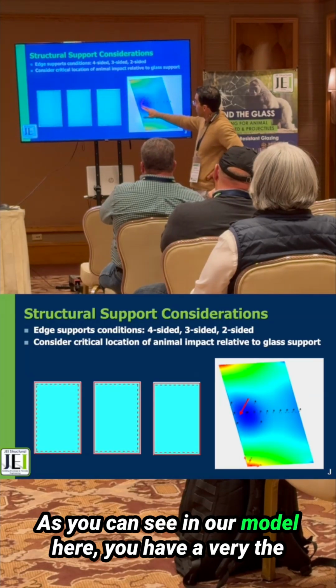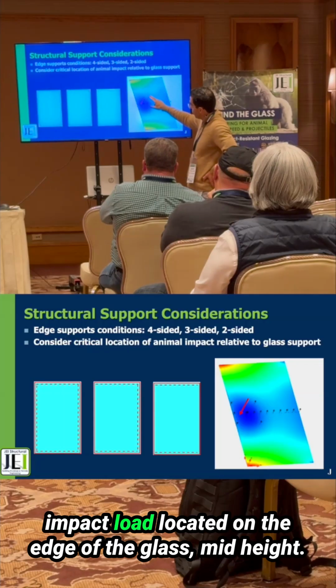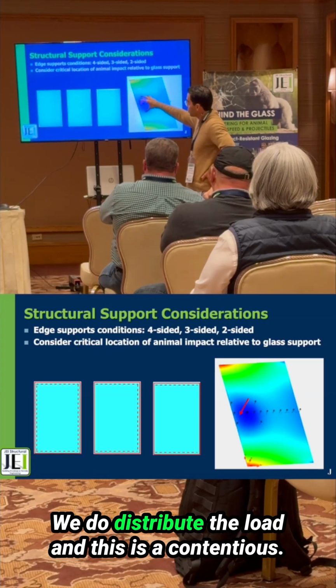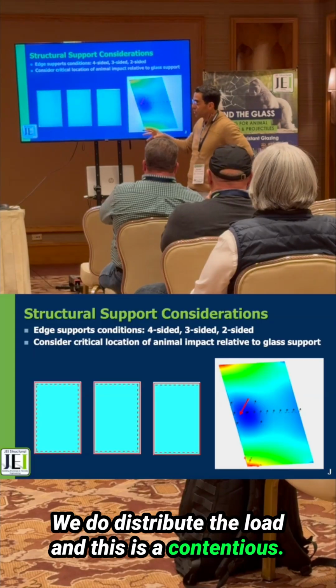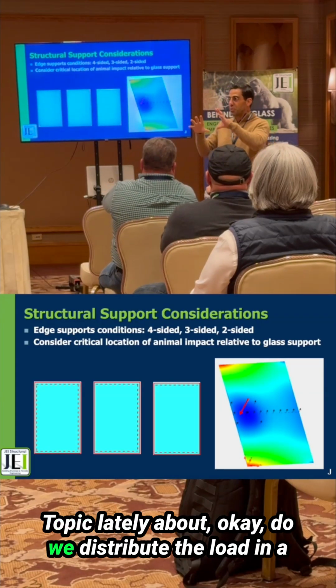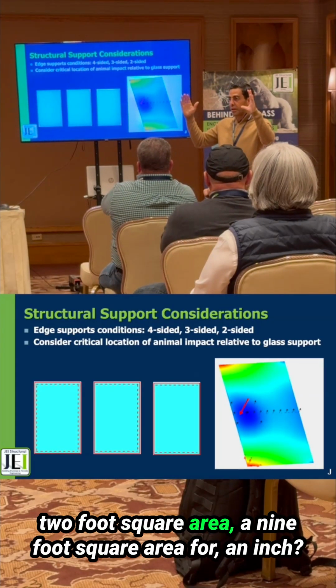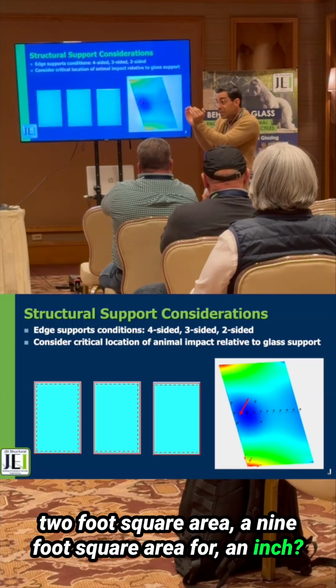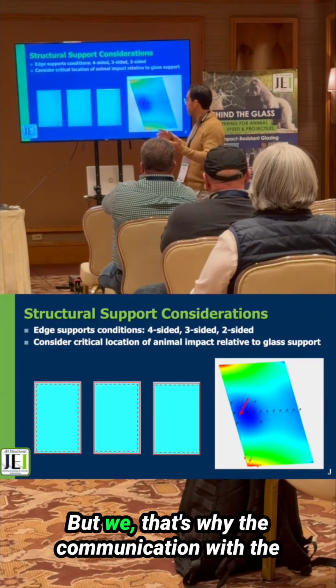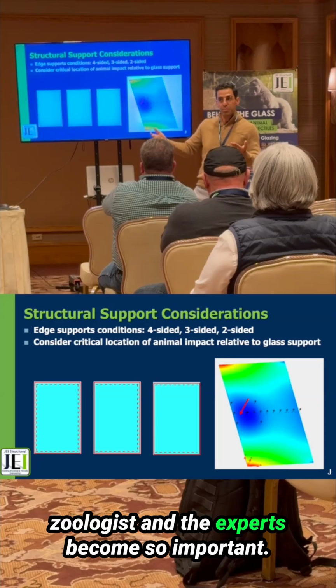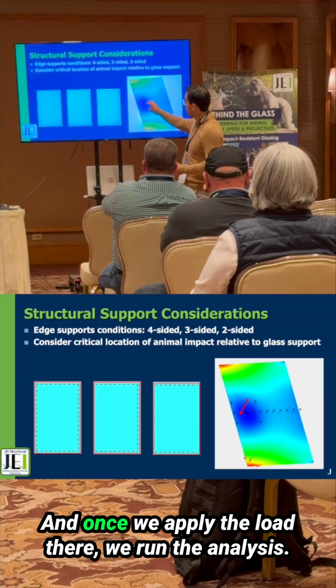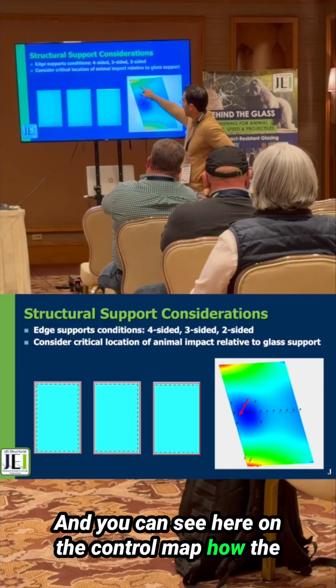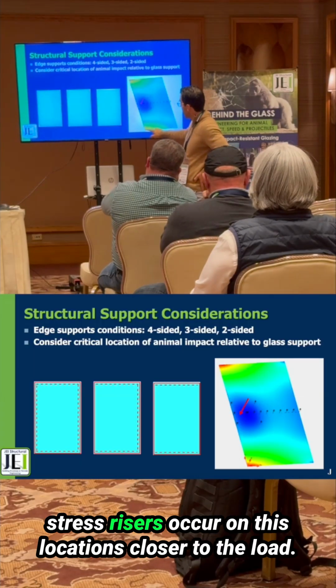As you can see in our model here, you have the impact load located on the edge of the glass mid-height. We do distribute the load, and this is a contentious topic lately about, okay, do we distribute the load in a 2-foot square area, a 9-foot square area, an inch? It varies. But that's why the communication with the zoologists and the experts becomes so important. And once we apply the load there, we run the analysis, and you can see here on the contour map how the stress risers occur in these locations closer to the load.